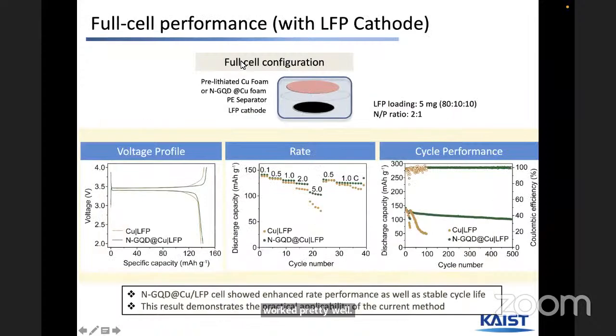Finally, we wanted to confirm whether it is possible to use this material as an anode for a full cell. One of the very well-known full cell materials, lithium iron phosphate, LFP, 5 milligrams, was used in the cathode, and the anode is pre-lithiated copper foam with NGQD, separated by a separator. It shows the very well-known single plateau in the charge-discharge curve, as a function of cycle number and C rate. Once the C rate is increased, the bare one comes down, but the NGQD case is much higher. So in longer cycles, the difference is very evident. A lithium metal anode with the NGQD layer incorporated is possible. We can see the possibilities, and its practical application is also possible.